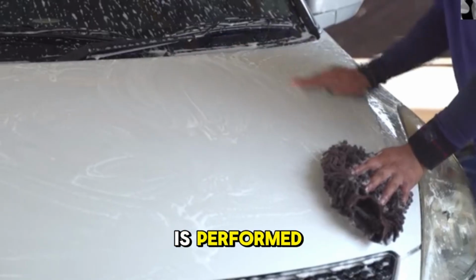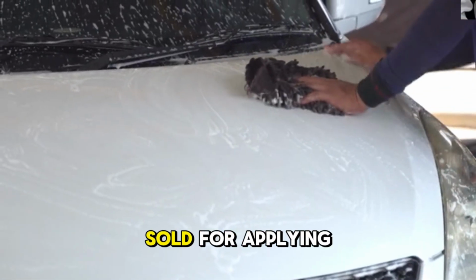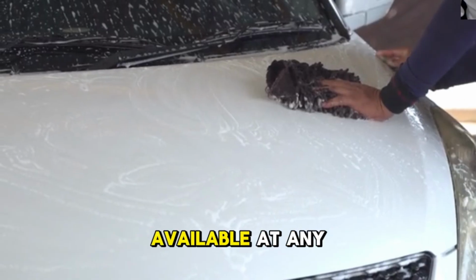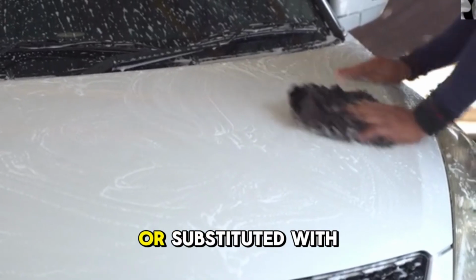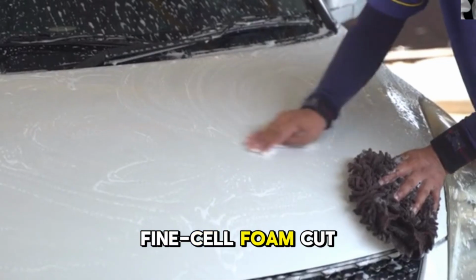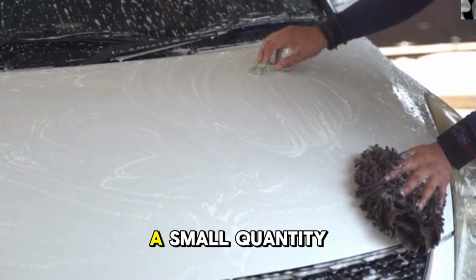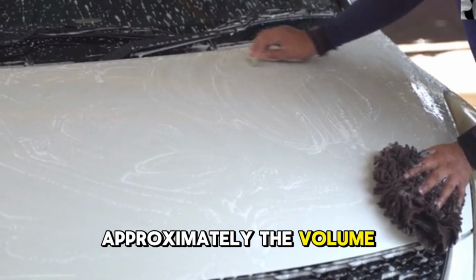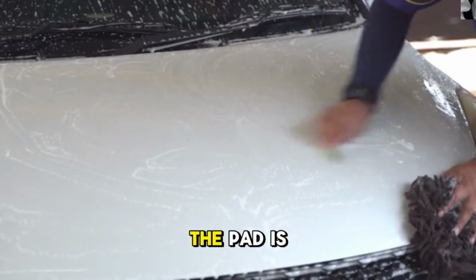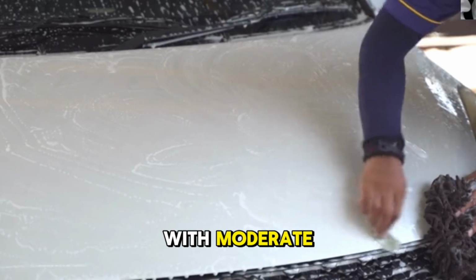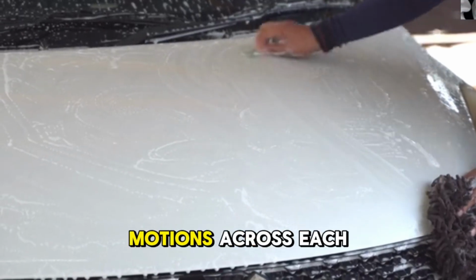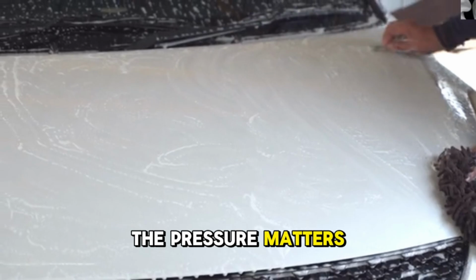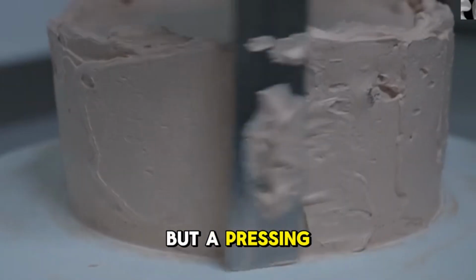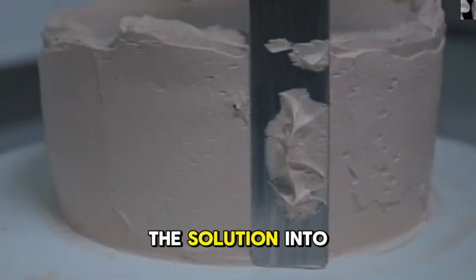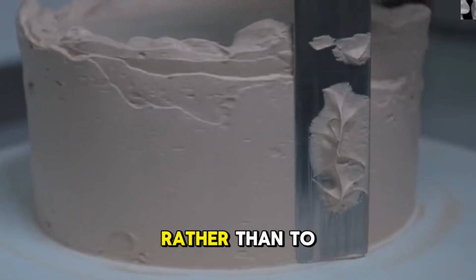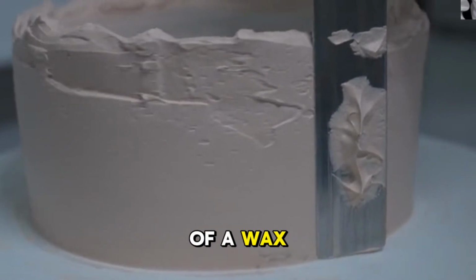The application itself is performed with a foam applicator pad, the type sold for applying polish or compound, available at any automotive retailer for minimal cost, or substituted with a piece of clean, fine cell foam cut from household packaging material. A small quantity of the resin solution, approximately the volume of a tablespoon, is applied to the pad. The pad is then pressed against the paint surface with moderate, even pressure and moved in overlapping circular motions across each panel section. The pressure matters. It is not a wiping motion, but a pressing motion. The objective is to push the solution into contact with the fracture openings rather than to spread it across the surface in the manner of a wax application.